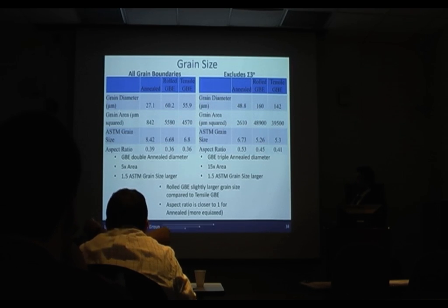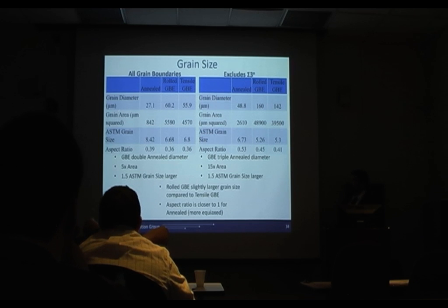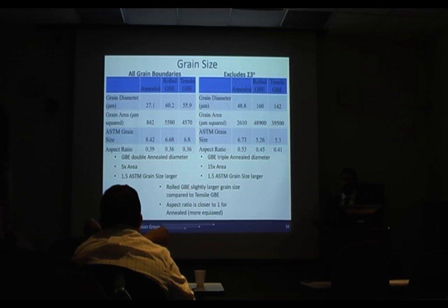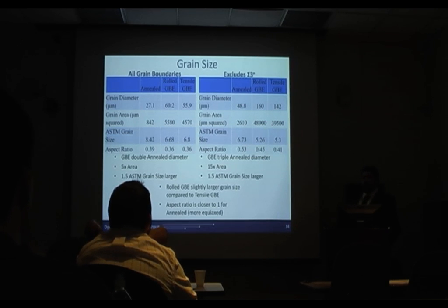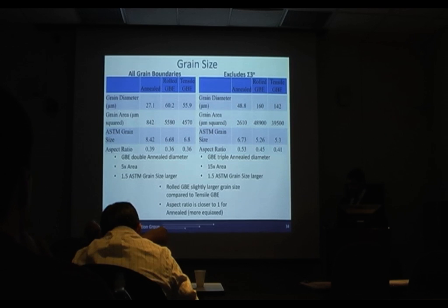And what we found was that the GBEs under the all grain boundary condition are about double the diameter and 5 times the area, and under the excluding sigma 3 to the n, it's about triple the diameter and 15 times the area, and in both of those it's about 1.5 larger on the ASTM grain size scale. The roll GBE is slightly larger compared to the tensile GBE in both, and the aspect ratio for the annealed is closer to 1, showing that they're closer to equiaxed.